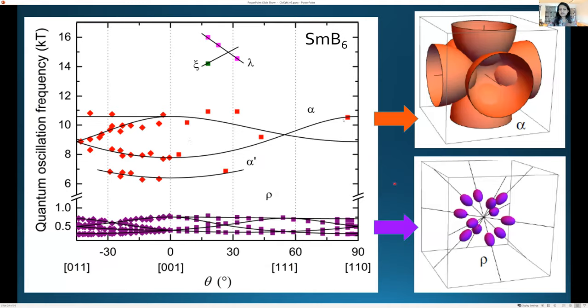So the black lines and the red lines I showed you before are essentially showing you simulations, if I were to take the same geometry as lanthanum hexaboride or the samarium hexaboride shifted band structure and simulate that. That looks not too dissimilar to the frequency versus angle in the measured hexaboride.